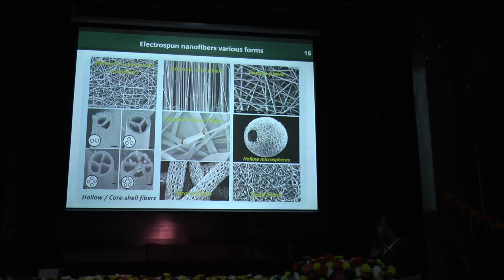So not only the random nanofibers, you can also produce aligned nanofibers. Also the porous nanofibers, hollow pore nanofibers, twisted-tip nanofibers. These are obtained just by controlling the speed of the collector and by using different solvents, you can get this morphology. So that's why electrospinning is a very simple technique to obtain various morphologies.